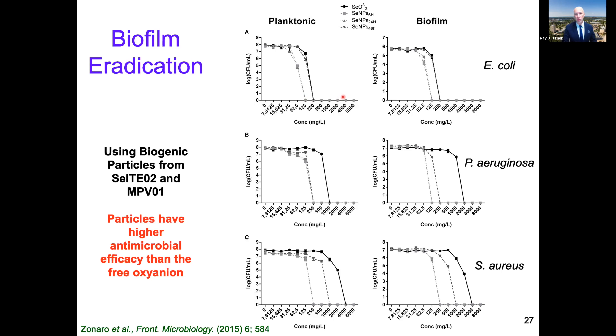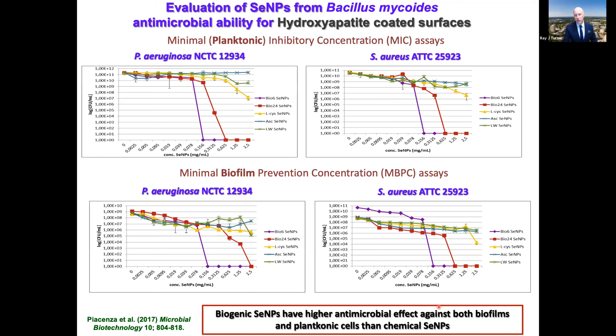Let me show some antimicrobial data. Here we compare the free selenite oxyanion of selenium against the nanoparticle form, testing planktonic bacteria — free-swimming bacteria as found in water — and biofilm, which is the surface-attached form such as the plaque on your teeth. Biofilm is more resistant to antibiotics and represents the real challenge. The biogenic selenium nanoparticles have the ability to kill off biofilm. Looking at Pseudomonas aeruginosa and Staphylococcus aureus, the selenium nanoparticles produced at different times are slightly different in size, with the smaller nanomaterial being more antimicrobial.